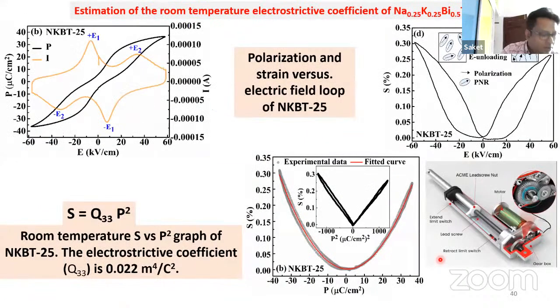Again, if you see, this is the solid solution where sodium is 0.25 and potassium is 0.25. Here you see two switching fields. In the loop, you can see that it's not like a ferroelectric, and not like an anti-ferroelectric either, but a combination of both the phases, ferroelectric and anti-ferroelectric.